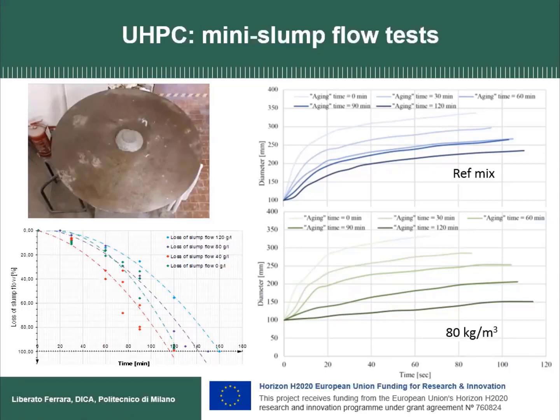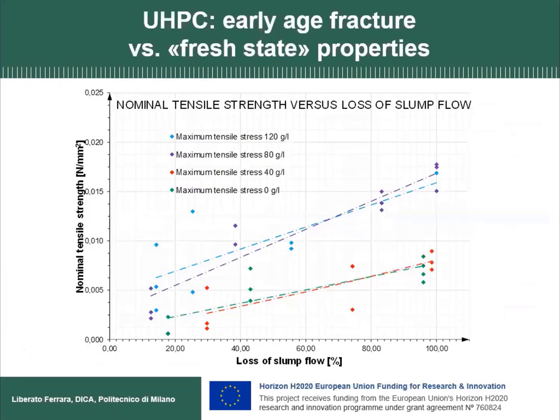We calculated the loss of slump. You can see there is a common trend, but with increasing dosage of the fibers, there is some change also in this curve. So there is an interaction between the fibers and the matrix in governing the evolution of the rheological properties.